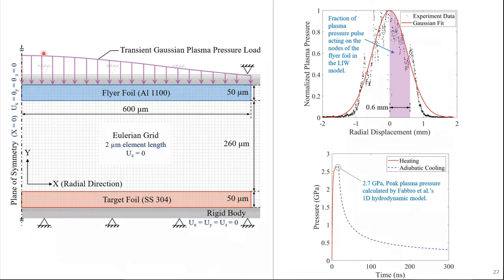And then again, I apply my plasma pressure, just like I did for LSP. It's very similar. It's exactly the same. Here we build a symmetric simulation for reducing the computational expense. So instead of having the double plasma, the double magenta on both sides, I just have half of it. And that's what you see over here. Again, we also have the same adiabatic cooling and heating profile to model the temporal profile of this plasma pressure pulse.